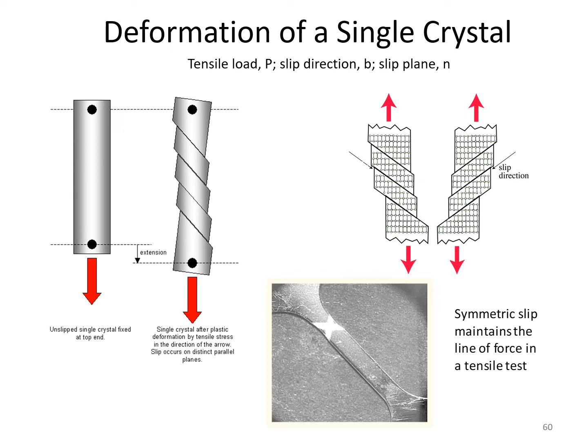The constraints caused by slip on one system can induce secondary slip, as you're pulling on a secondary slip system to keep the tensile specimen aligned with the load line of the load frame. So this here shows slip on two different slip planes, and that's typically how a tensile specimen will operate.